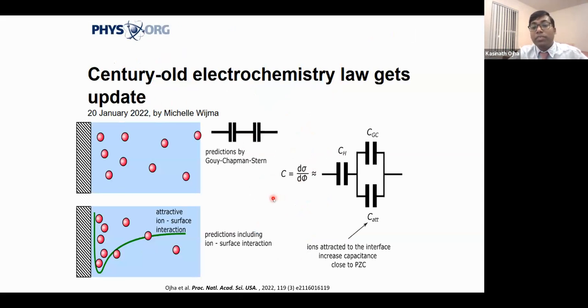And then we derived this model. In the normal double layer structure, the known theory, you have an electrode and electrolyte, with some ion distribution over the distance, and we call that Gouy-Chapman-Stern theory. Basically we have two capacitors in series. That's the textbook theory. Now what we observe is that there are ion-surface interactions, and that leads to an additional capacitor, and all the ions move closer to the surface. So there is accumulation of ions happening. It's happening on platinum, it's happening on gold, and to some extent silver.